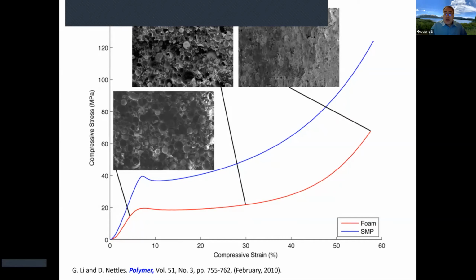When you prepare shape memory polymer-based synthetic foam, it's just like what you do for a conventional thermoset polymer-based synthetic foam. You mix the glass beads or other microspheres with a resin, add the hardener, and then you cure it. Even the mechanical behavior is very similar to conventional synthetic foam. If you look at the red line, you can see the elastic deformation, yielding, plastic flow or buckling of the microspheres, even some crush, and then finally densification. That's exactly the same as a conventional synthetic foam.